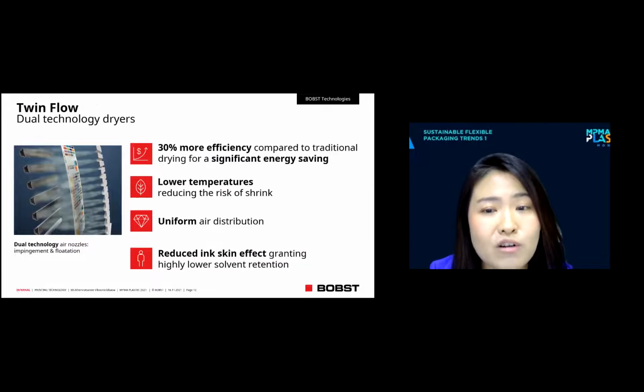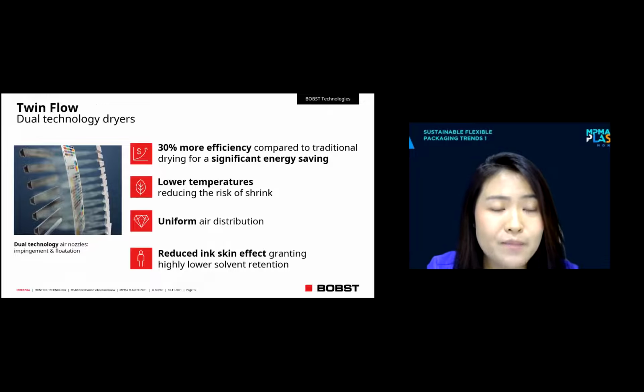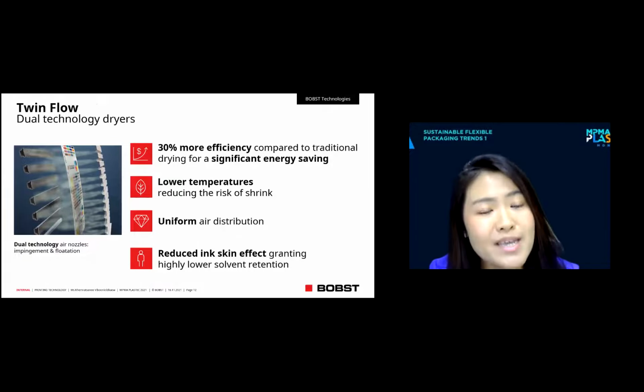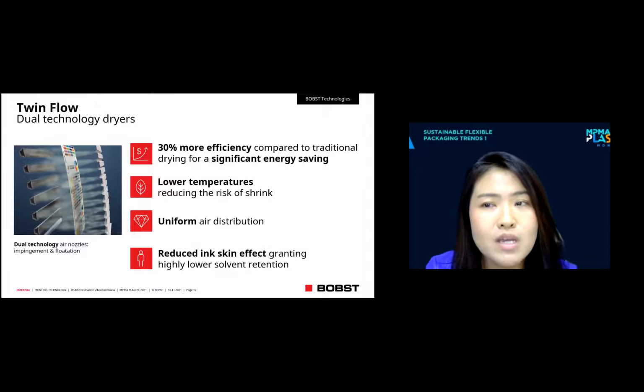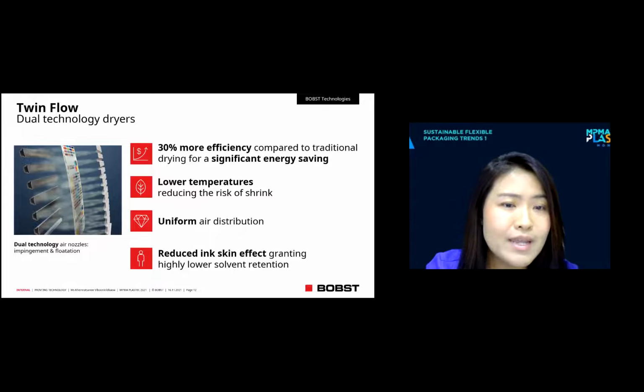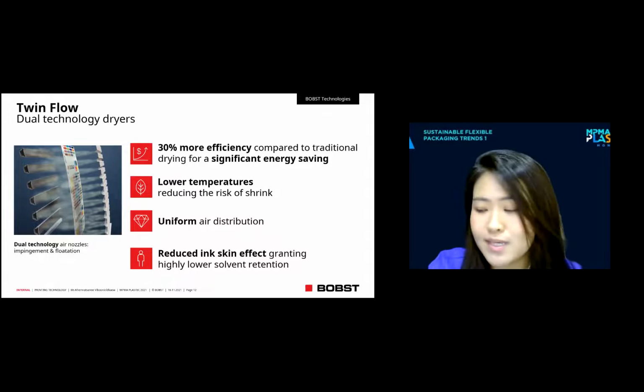And for the dryer technology, we also have a dual dryer system. You can see on the side that our dryer can come to the front and the back. Especially with this kind of dryer, we can reduce a lot of the skin effect and lower the solvent retention. With the lower temperature, because for MDOPE we're talking about a temperature like 40 to 45 degrees Celsius to handle the sensitive MDOPE film. We ensure that our dryer and temperature will fit sensitive materials like MDOPE.